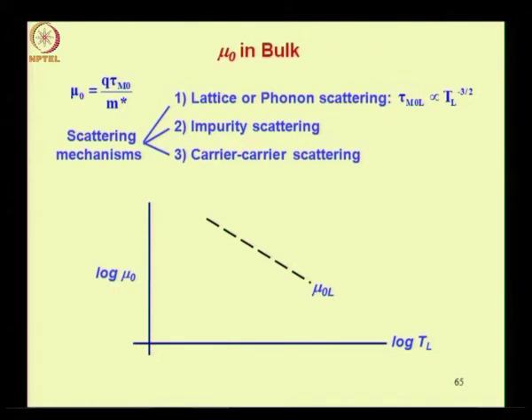Now quantum mechanics gives us the relation between the momentum relaxation time for lattice scattering and the lattice temperature. So this relation is obtained as tau m0l is proportional to TL power minus 3 by 2. Now since your mobility is proportional to tau m0, therefore the mobility also is proportional to TL power minus 3 by 2. So it decreases as TL power minus 3 by 2 for lattice or phonon scattering. Now that is what is depicted here in the graph. Since the relation between mu naught and TL is a power law, we have chosen a log mu naught versus log TL axis, because on such a choice of axis the behavior would appear as a straight line.